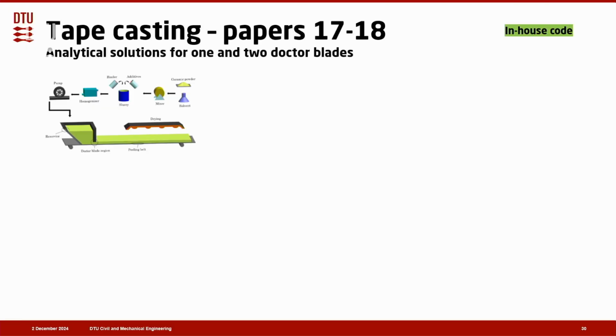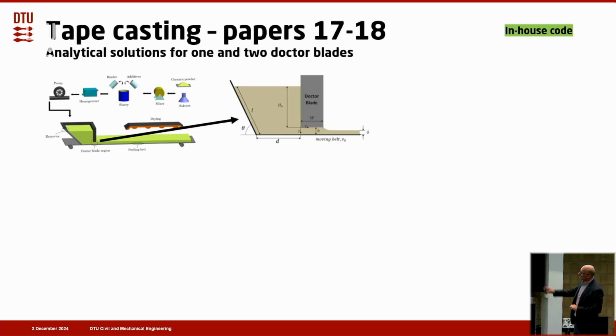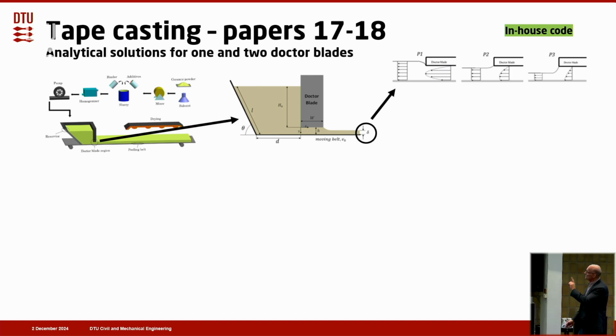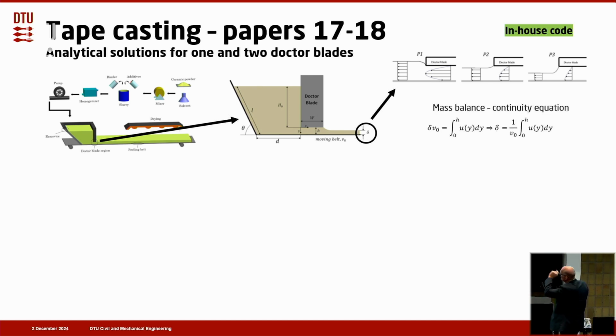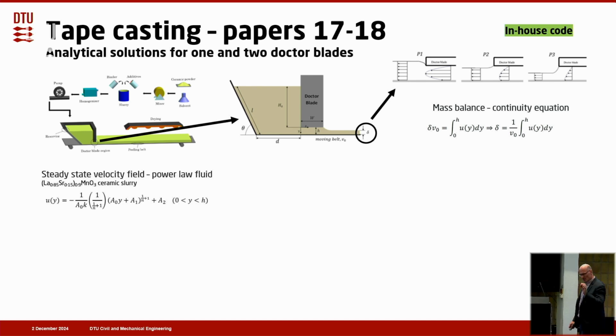Now, tape casting, this process here where you make very small tapes to be used in the electronics industry. This is the doctor blade region where it flows out, and this is where all the magic happens, you could say. What you're frequently interested in here is the thickness of the tape, because you want to control how thick it is, and that thickness you can actually calculate if you know the velocity field. Because if you know the velocity field, you can use the mass balance, the continuity equation, and then you can find the thickness. So what we did was that we suggested a steady-state velocity field solution for a power law fluid. In literature, at that point, it was only Newtonian fluid that was suggested.